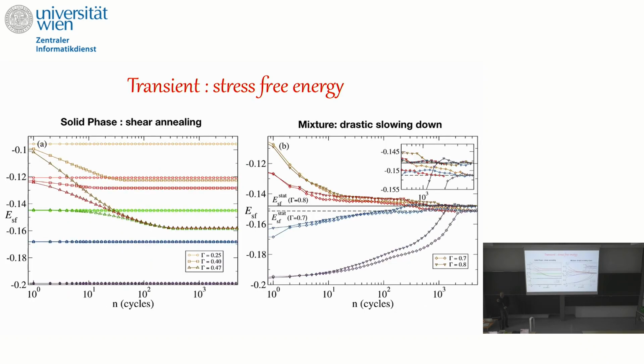Okay, so I want to spend a few words about how much you have to shear in order to reach this steady state. What we see is that in the solid phase it is quite fast, in the sense that of the order of 20, 30 periods, you already reach the energy and you are in the steady state. So when you are in the solid phase, you should observe the shear annealing quite well, okay? When you are in the mixed phase, in order to observe a perfect stationary state, it takes a much longer time. You see here, you have all this plateau here, here, and here.